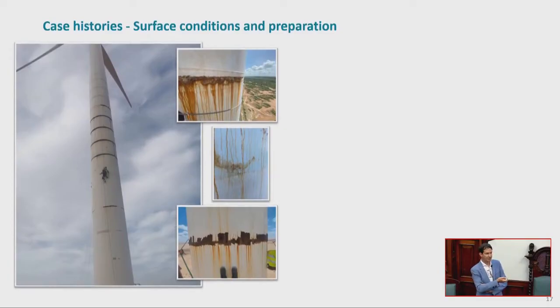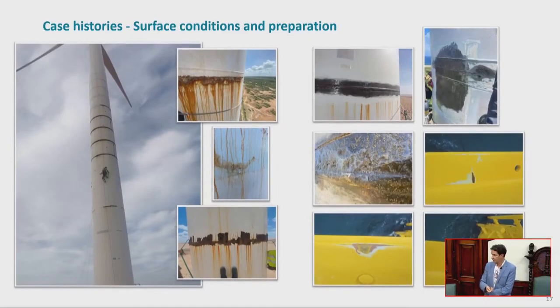But we have to be aware that when we do the test, we put it on, as you saw with one of the plates, a small plate. We didn't take into account the movement of the wind, of the whole tower. We don't know what the failures are on that tower over there, but you can see that almost every weld failed. Was the heat affected zone too big? Did the whole tower become too flexible or too rubbery? And that's why the coating popped up? We don't know. But that's where we also started to explore all these things, like why is this happening?